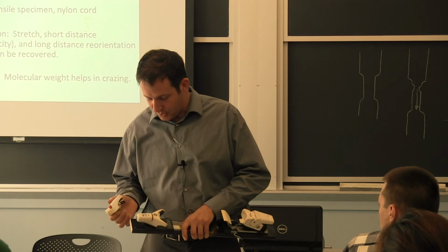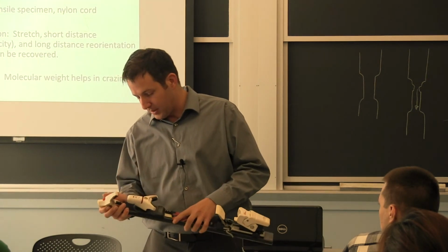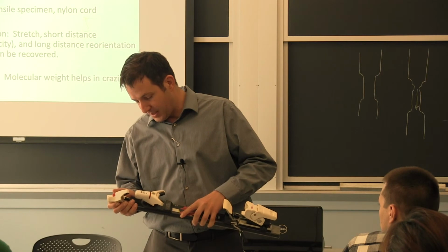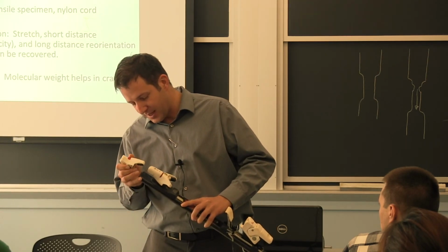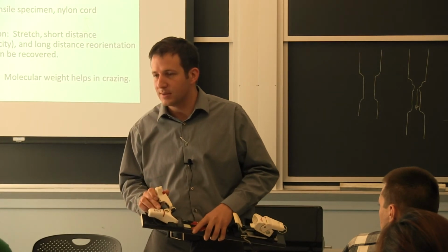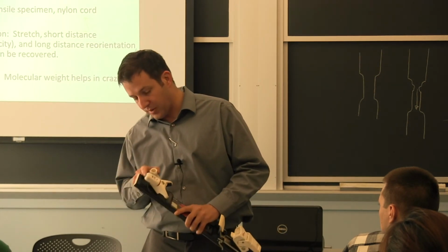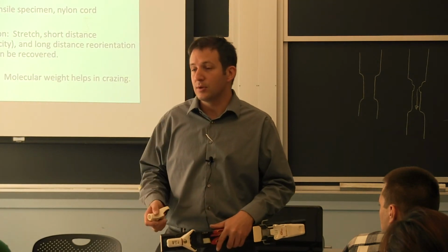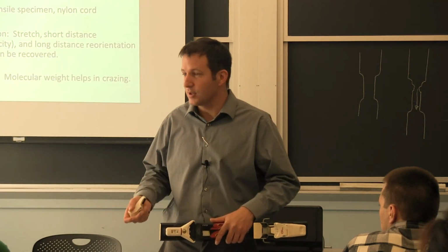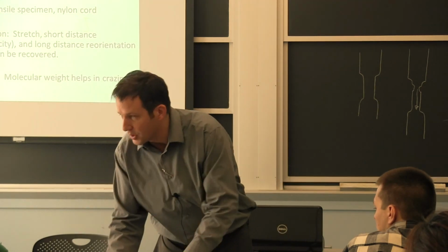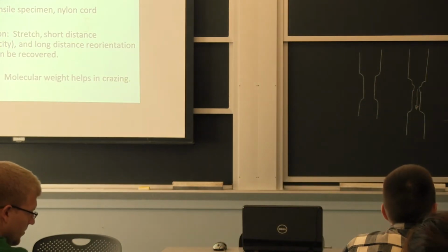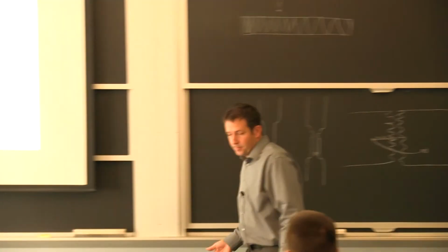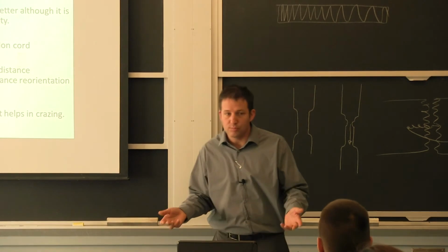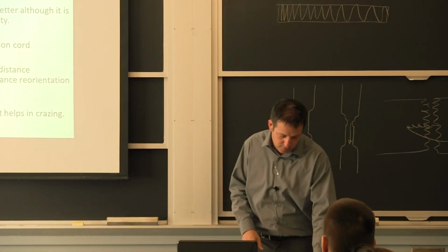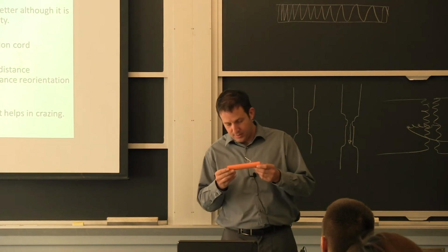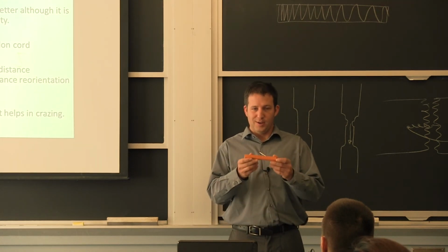It's because this material had a time limit in terms of the inhibitors and the oxidation, the antioxidant package that comes with it. And when you exhaust it, now it becomes very, very brittle. It doesn't have anything to do anymore with how good the molecular weight is. You can start breaking chains because you have oxidation reactions going on. So the oxidation is one way to break chains. The sun, the UV light, is also a way to break chains. You need something like that to break the molecules inside the material. Solvent, even oil, is a way to break chains.